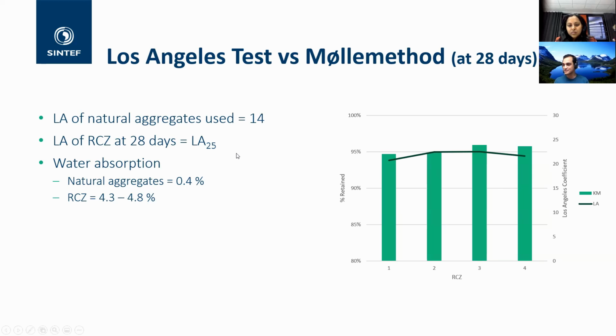And the aggregates that we got from dry washing of concrete rock have good properties in terms of abrasive strength. The Los Angeles coefficient was 25 and less. The flakiness index was reduced a lot, but it has high water absorption compared to the natural aggregates that we use. That's one of the issues that we saw with these aggregates.